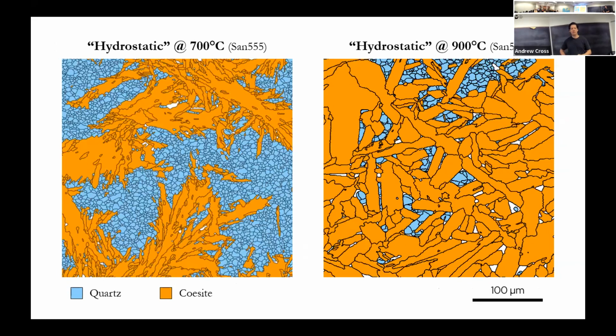And we can again turn to the EBSD data to think about why that might be. So we've got a hydrostatic experiment. This time it's 700 C, and then hydrostatic at 900. So this is the sample. This is one of the maps we've already looked at. Again, blue is quartz, orange is coesite. So we've got big tabular grains of coesite at 900 C. At 700 C, we see that the grains are much more needly. And particularly when you look at the orientation maps of these, you'll see that these are kind of splaying needles of coesite, much narrower and very long.